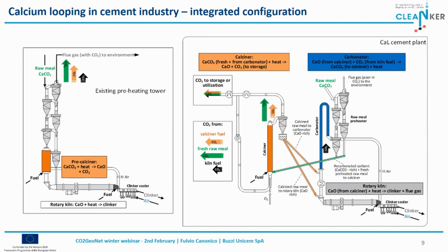Of course, this loop doesn't work for eternity, so after 5-6 cycles, the calcium oxide is no longer able to capture CO2 in an efficient way. But this is not a big problem if we are integrated in a cement plant, because we can use this calcium oxide as a component of the kiln. Next slide, please.